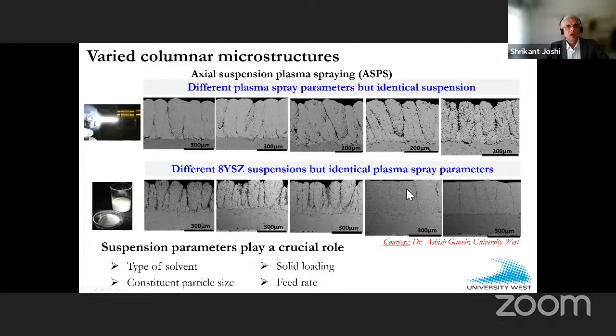So some quick results from our own work in our thermal spray group here by my colleagues. One was we have been using SPS for thermal barrier coatings for a long time. And we have demonstrated that one can almost control the columnar structure at will, right? You can control it for an identical suspension by varying the plasma spray parameters, or you could actually use different kinds of suspensions, right? By varying the type of solvent, by varying the loading rate, of course, and also playing around with the particle size that constitutes the suspension, right?